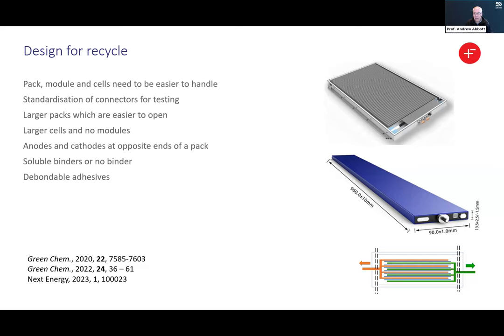They've got anode and cathode chemistries at opposite ends, which means that it's easier to separate out those anode and cathode chemistries mechanically. They've got very few connectors, almost no glues used inside their modules. And what we've got is sort of larger cells with no modules. So we've got a straight cell to pack structure. What we're trying to develop, as are many other groups, is more soluble binders or no binder based systems. And these ease the way in which we can separate those active materials away from the current collectors.